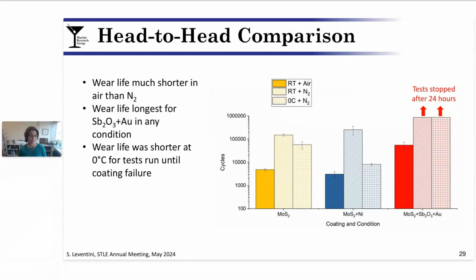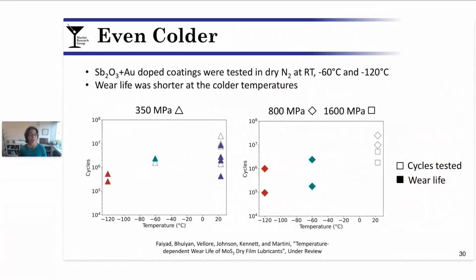And lastly, looking at the temperature of the test, the temperature results for the test that did fail, these are the square hashed bars, we can see that for the pure MoS2 and the nickel-doped MoS2, the wear life is shorter in the colder condition. So let's talk about now even colder. So looking at our best case coating, the antimony oxide gold coating in dry nitrogen, tests were performed at -60 and -120. So even colder.